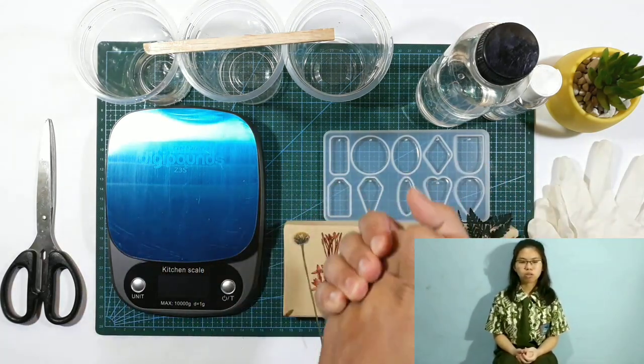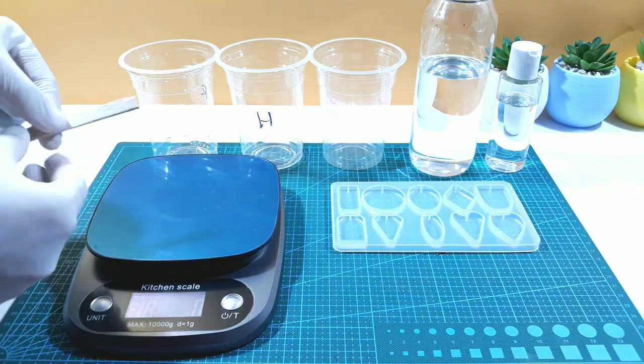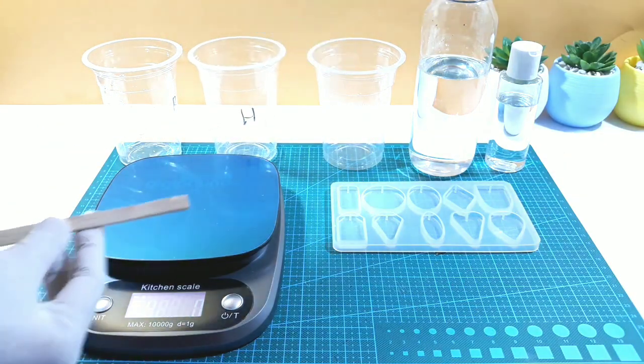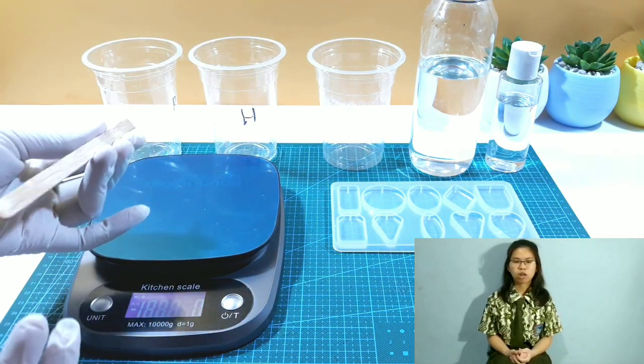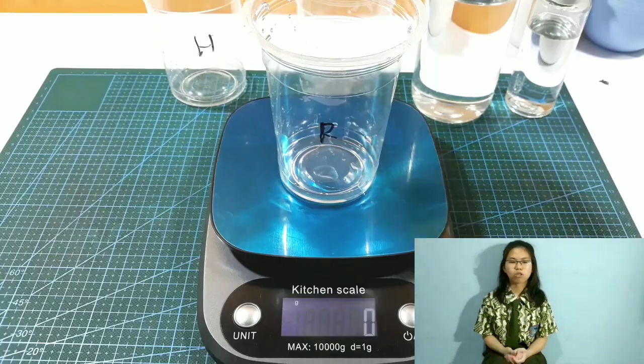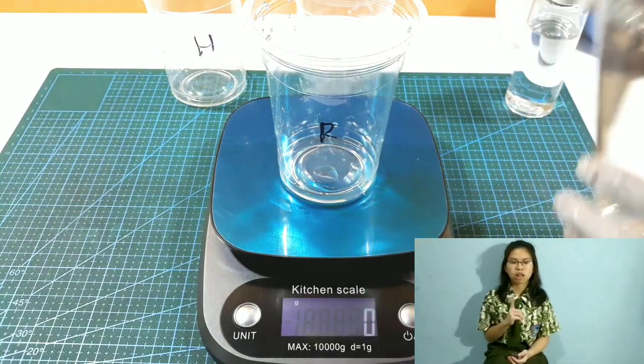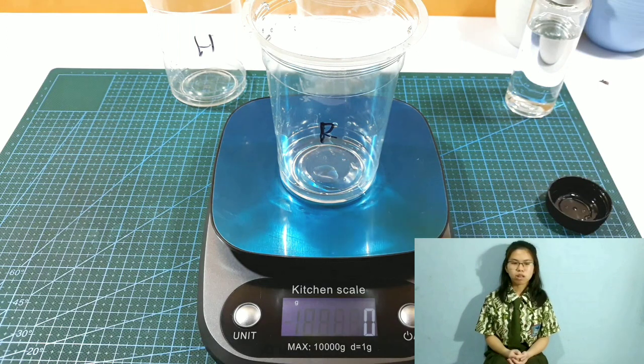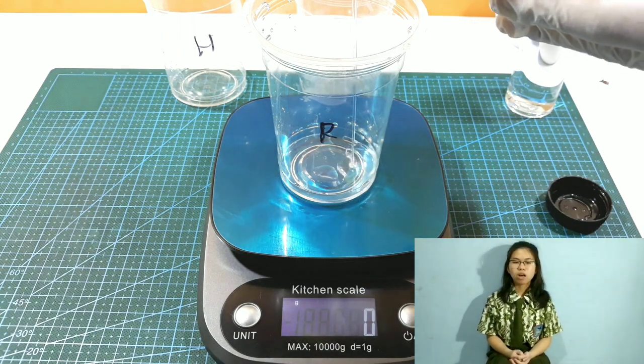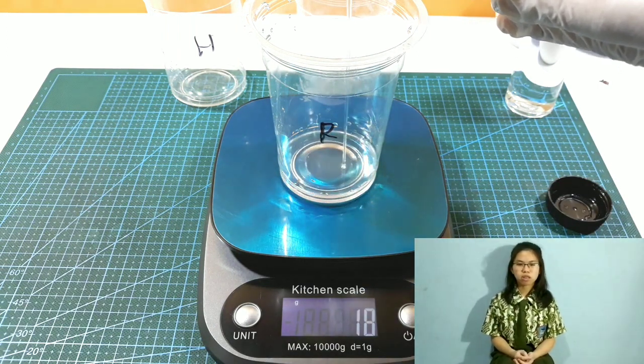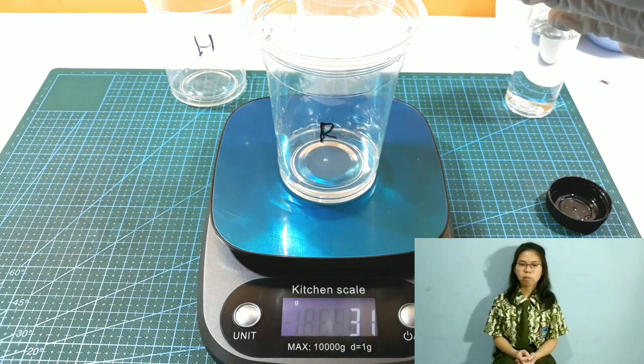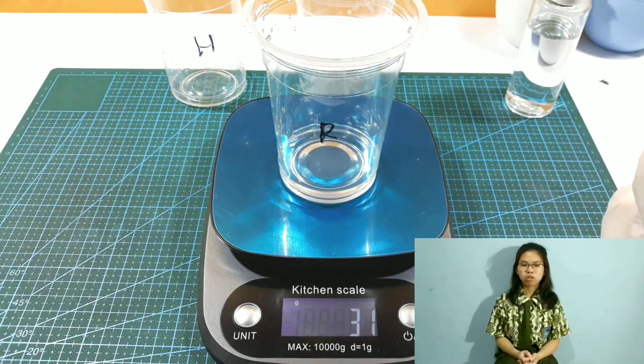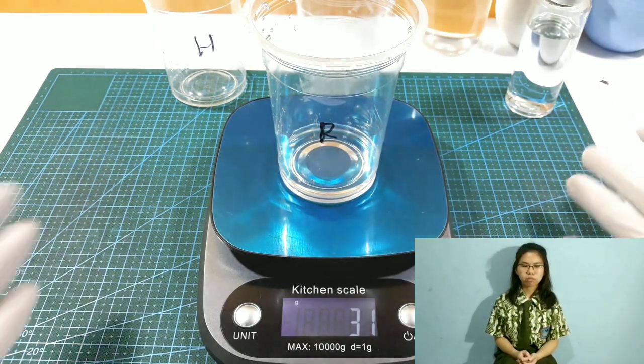Now we're going to show you how to make this resin-based product. First, pour separately in 2 cups the resin substance and the catalyst, with a ratio of 3 for the resin substance and 1 for the catalyst. Mix these 2 substances in a new cup and stir it well with a stick. After you finish stirring the mixed substance, wait a little bit until the bubbles that form decrease, but don't leave it for too long because it will harden.